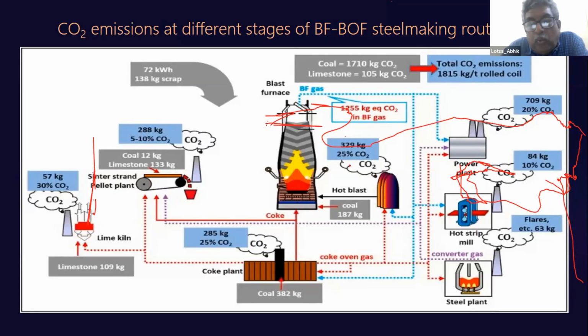But the sinter plant, the coke plant, the hot strip mill, the steel plant, the lime plant, they are also emitting carbon dioxide to the atmosphere. So in totality, the total CO2 emission is 1,815 or almost 2,000 kg of carbon dioxide per ton of rolled coil. For each ton of steel, each ton of rolled coil that we see in the market, they have already produced two tons or 2,000 kgs of carbon dioxide, which is going into the atmosphere.